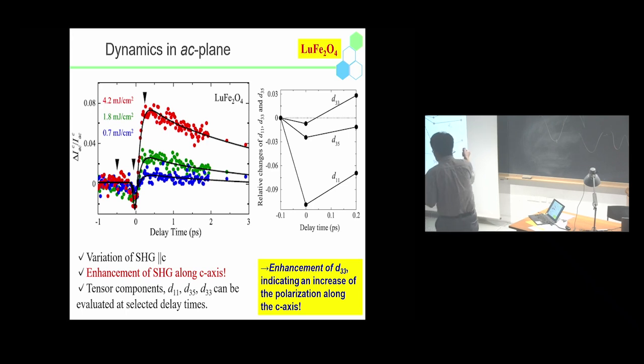By using this data and the previous data, we extracted the tensor components at selected delay times denoted by those triangles. This is the time dependence of the tensor components d11, d33, and d35. The d11 component reflects the polarization in the ab plane, and the d33 component corresponds to the c-axis polarization. The d11 component still decreases. However, the d33 component is increased by the photoexcitation. So this is the point: enhancement of d33. This indicates an increase of the nonlinear polarization along the c-axis. This is the second conclusion.